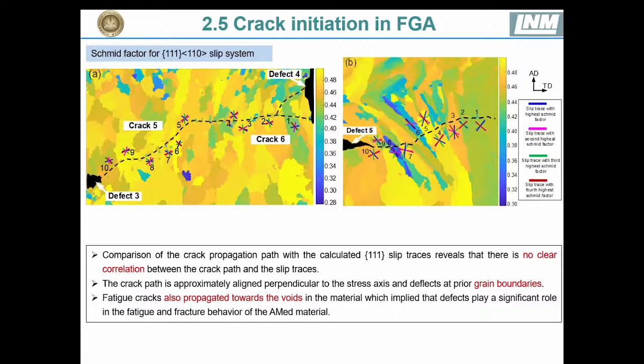And here in this slide, the Schmid factor for the {111}<110> slip systems corresponding to the area under tension around this area was calculated. From this analysis, we can see that the grains through which the crack passes are numbered, and the slip traces of the correspondence are identified. And we can see that the crack path is approximately aligned perpendicular to the stress axis and deflects at prior grain boundaries.